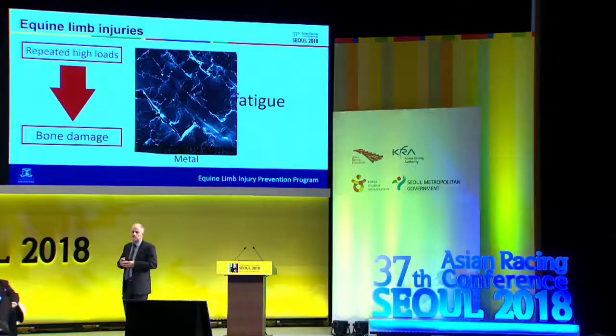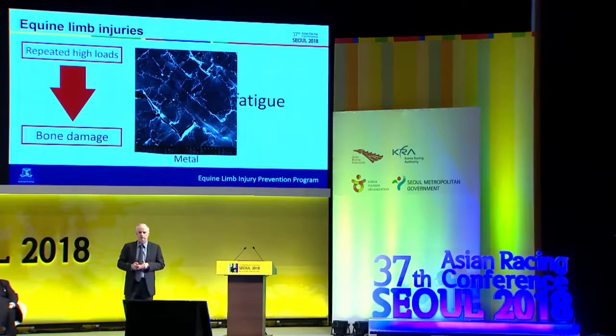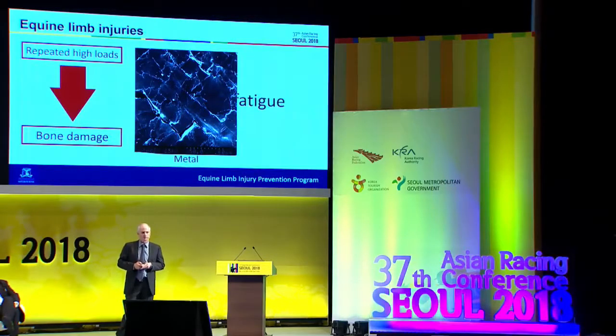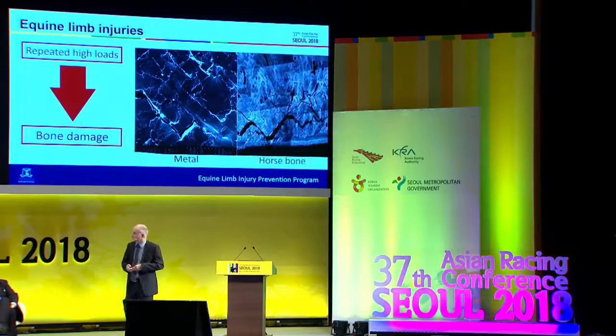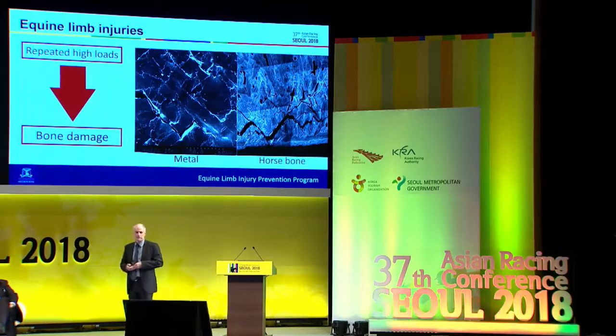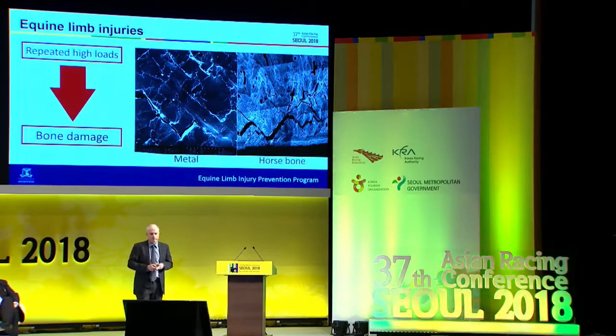And there's an example of metal fatigue, a piece of machinery that's been undergoing cyclical loading and has developed these microcracks, these crisscrossing microcracks that you can see, one major crack through it, and that piece of metal has eventually failed. Well, this is horse bone with exactly the same appearance under the microscope, crisscrossing microcracks and a major crack through it. So horse bone is just like any other material. We apply enough load to it, it will eventually fail.